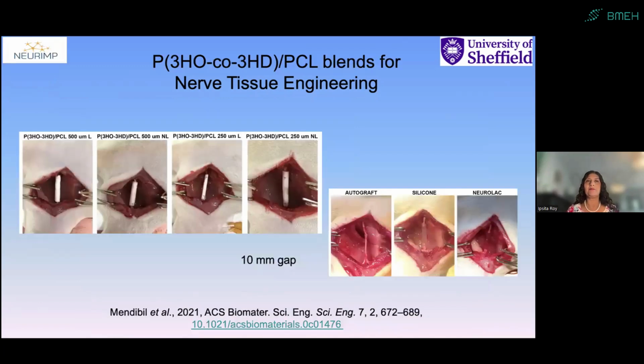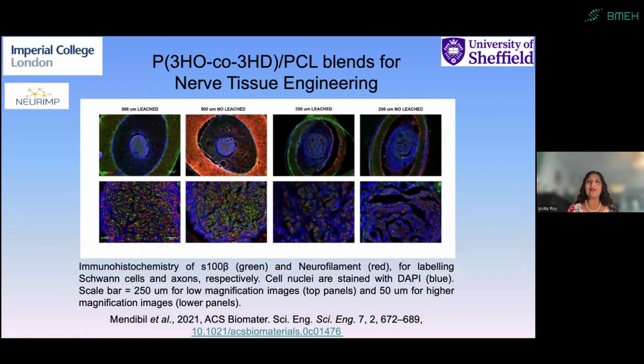And here we did also another study with a European project in collaboration with many partners. And here you can see we took a blend of P3HO-co-3HD, which is the hydroxyoctanoate decanoate copolymer, a medium chain length PHA, blended it with PCL, and those are the tubes that we put within the broken nerves. And here we had an autograft, a silicone tube, and Neurolac, which is the currently used nerve guidance conduit by the surgeons. So when we did the immunohistochemistry, we observed beautiful regeneration in all the cases.